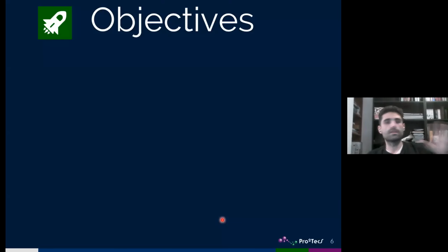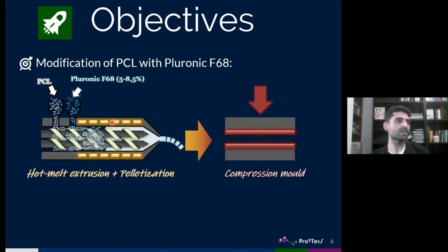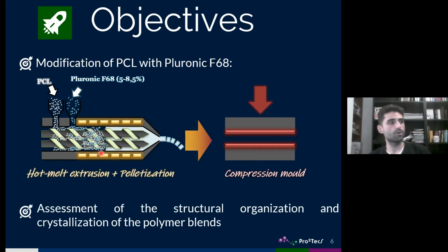Well, with that in mind, the aims of this study were, first, modification of PCL with Pluronic. There are so many kinds of Pluronics, but we took Pluronic F68 at two different concentrations, 5 and 8.5 percent, using hot melt extrusion followed by pelletization, and then the obtained pellets were compression molded, obtaining the final polymer blend. The other aim was the evaluation of the structural organization and crystallization of those biodegradable polymer blends.